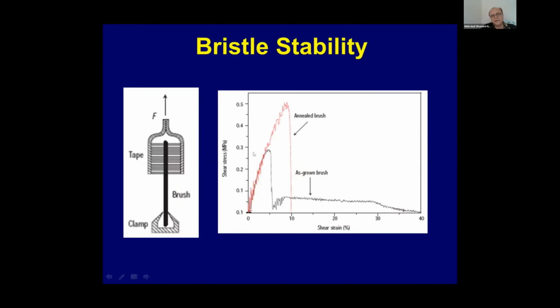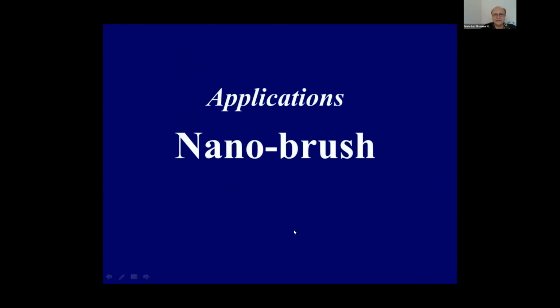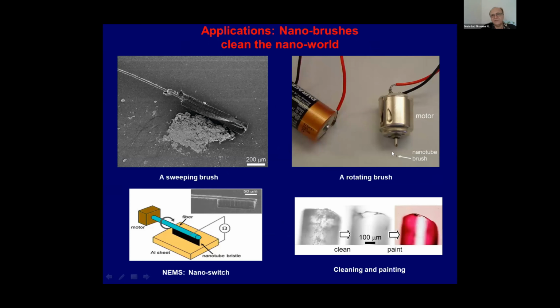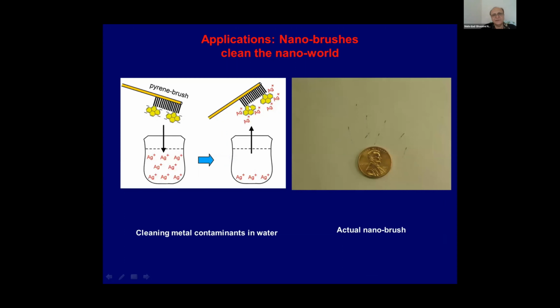We can even improve the adhesion of the nanotube to the stem of the brush by annealing, so double the increase, double the shear strength of attachment of the carbon nanotube to the stem of the brush. So there are many applications: nano cleaning, micromotor, nanomotor, electronic switch, and cleaning inside microcapillaries, that's a medical application. Also, you can functionalize the brush with, say, a pyrene system, and that will attract harmful materials, ions in industrial waste water, like mercury, silver and cadmium. This is the size of the nano brush compared to a penny. So those are small, our carbon nanotube, this is the stem of it.